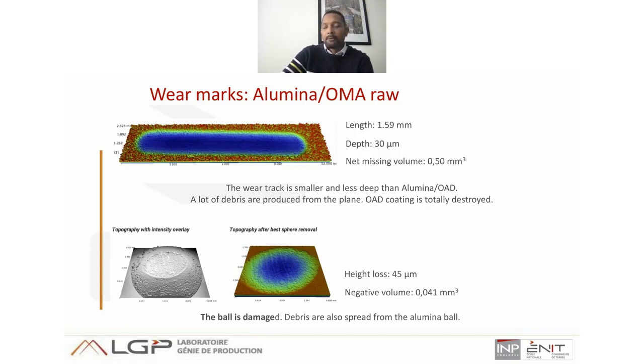In this case, I remind you that we also have the brittle part of the coating with the dense part. The friction and the wear are principally due to the production of debris from the brittle part. The surface of the ball is now damaged, and there is debris that spreads from the alumina ball in the contact.